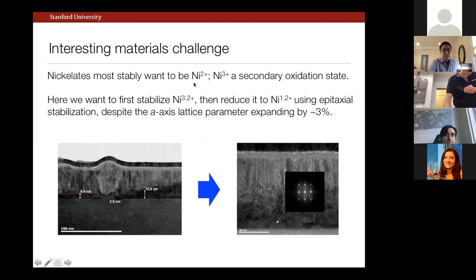As I said, the nickelates most stably want to be nickel 2+. Nickel 3+ is a secondary oxidation state. And from a chemistry point of view, what we're trying to do is rather extreme. Namely, we're trying to stabilize a very unusually high oxidation state, so formally something like nickel 3.2+, which is already very hard. In bulk, it would require high pressure oxygen, for example. And then we want to reduce it to a very unusually low oxidation state,